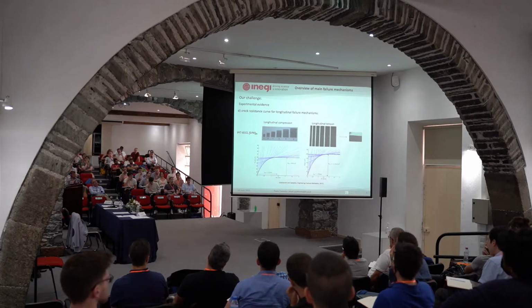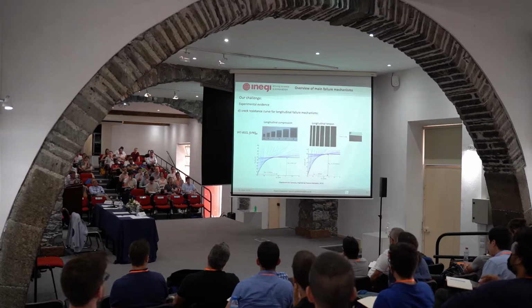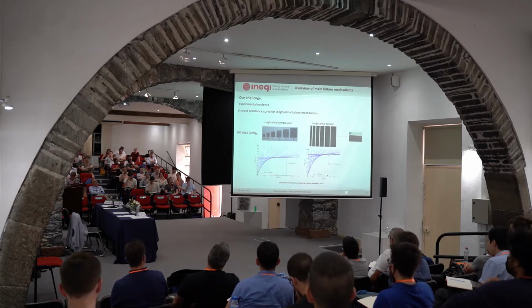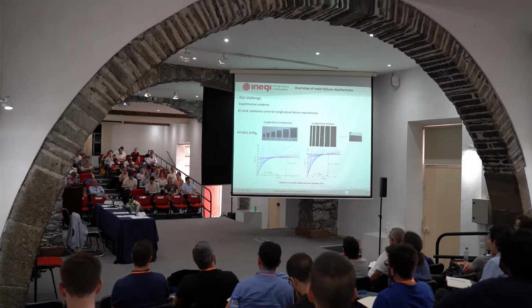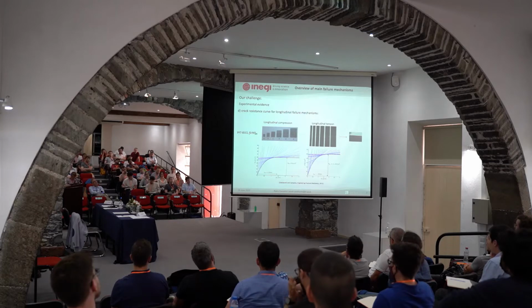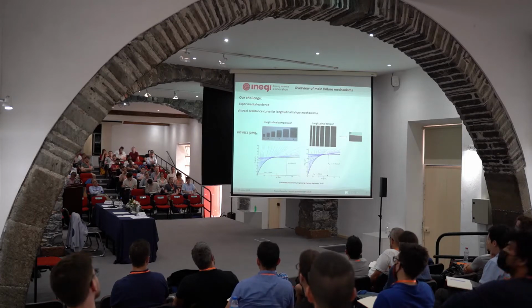You look at crack resistance curves, both for delamination, especially when you use glass fibers, where there's a huge R curve effect, but also for longitudinal failure mechanisms. So you can see here, if we apply longitudinal compression, so basically what we're doing here. It's very complicated to simulate or to obtain R curves in composites, especially for the new generation of composite materials, using the compact tension specimens, in my opinion.